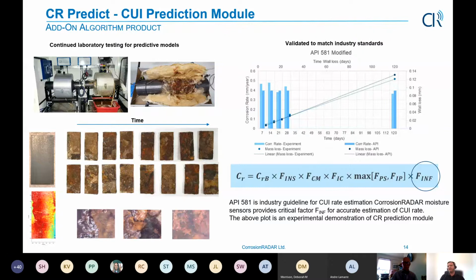Say, predict corrosion rate. In this case, this is an example of laboratories where we have various third-party laboratories, including some research laboratories, universities, and our in-house laboratories. So we do a lot of testing in this. Say ASTM G189 shows that if you have a pipe, we put a sensor in it and let it corrode. We put the coupon in as well to monitor the weight loss over time, and we benchmark it with API 581 or similar, say DNV models or API 581 models.